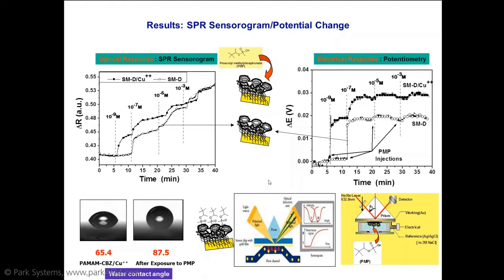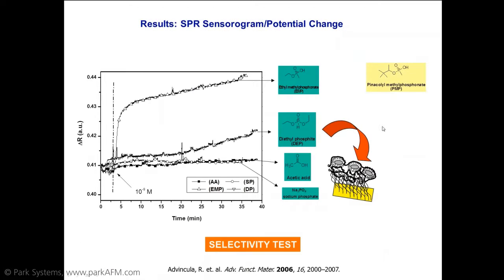In fact, the modification of the surface by the analyte and its presence actually changes the contact angle or wetting of the surface. We did this verification with potentiometry, and it showed the same result, that the presence of copper enhanced the detection limit up to 10 to the -9 molar. So we hence use this procedure for all our tests. Another is that of selectivity.